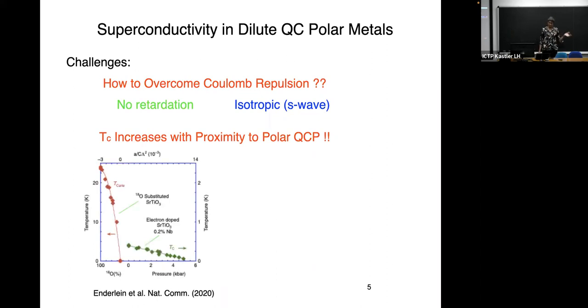In the experiments of the Cambridge group, Gil Lonzarich and colleagues, they find that there is an enhancement of TC as you approach the quantum critical point. So even though the electrons cannot couple directly to the critical boson, they definitely know about it, and you can enhance TC with that. So how does this work? Because remember, the critical mode is a transverse optical phonon. It doesn't couple to the electron density. Another way of saying it is it breaks inversion symmetry. You can't couple to the electron density.